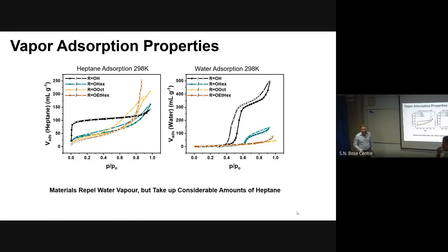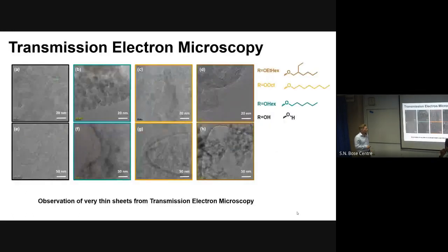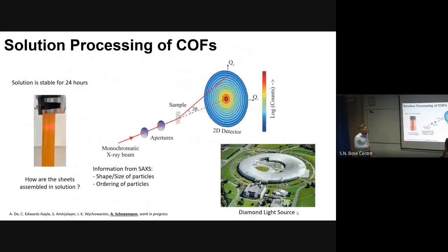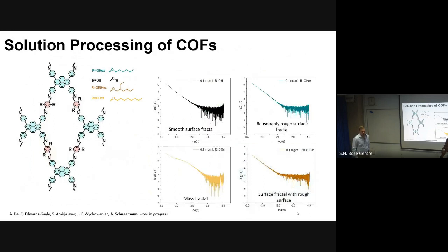With SAXS, small angle. So that 24 angstrom. So what? Because normally if you have particles of a similar size, they arrange in a fashion and you get some signal in SAXS. But in your case, all these particles would be of different sizes. Yeah, I mean, this is how it works for mesoporous carbons, for example. You have a pore size repeating, and you see the diffraction at that distance. So I imagine that those guys are swimming in solution, and if you have these side chains, they are probably stabilized better, maybe through interactions with each other, and then they give this scattering.